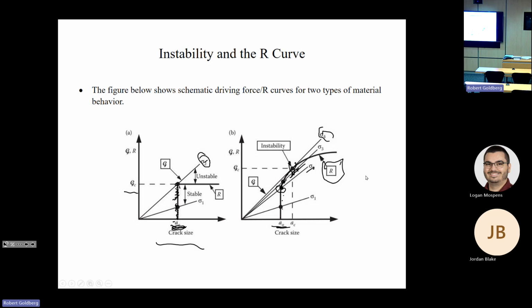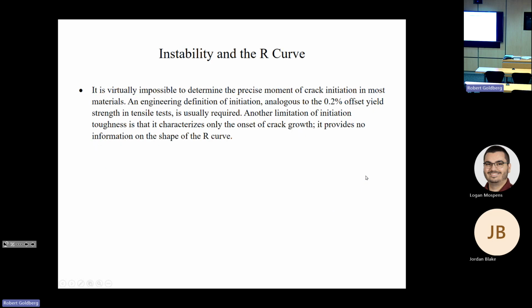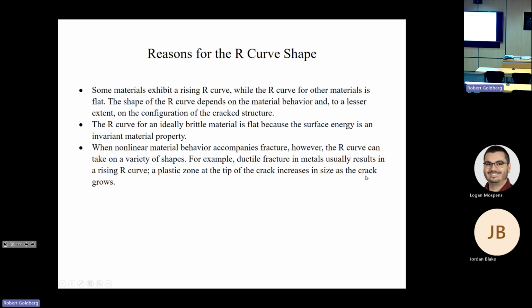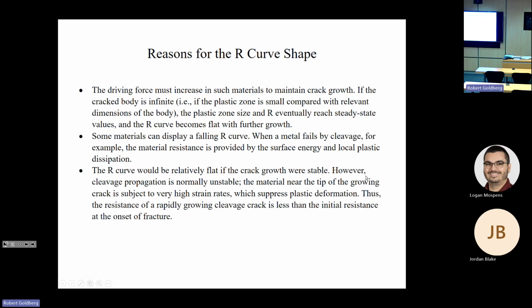However, for metals, where we have some localized or not so localized plasticity taking place, for a nonlinear material behavior, the R curve can take on a variety of shapes. For example, ductile failure in metals results in that rising R curve that we showed, because the plastic zone at the tip of the crack increases in size as the crack grows. This means we'll have a growth in resistance relating to the plastic flow, because when the material is deforming plastically, the energy that may go into the propagation of cracks instead goes into the propagation of the plastic flow in the material. So the driving force has to increase in these materials to maintain crack growth.